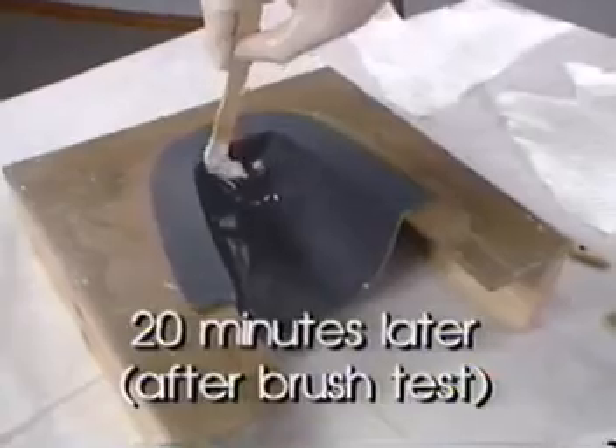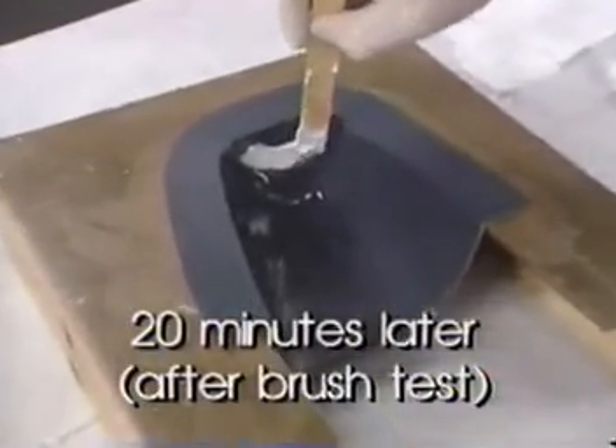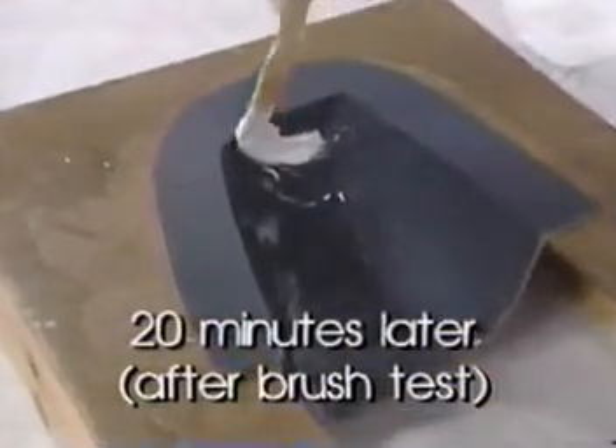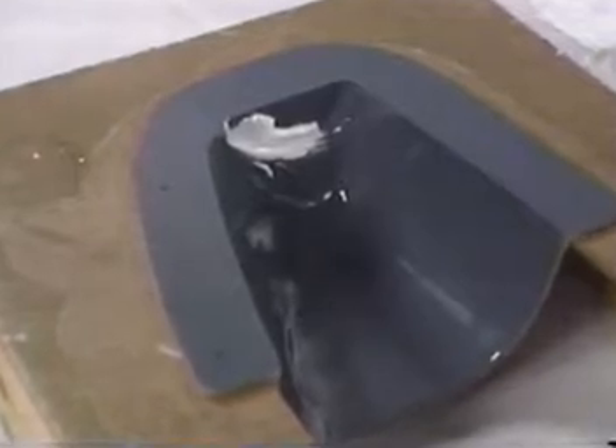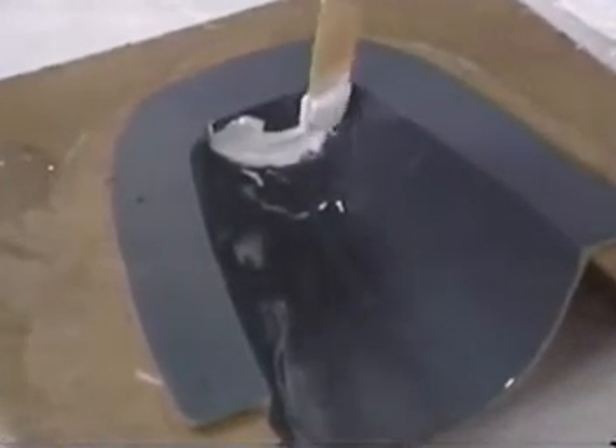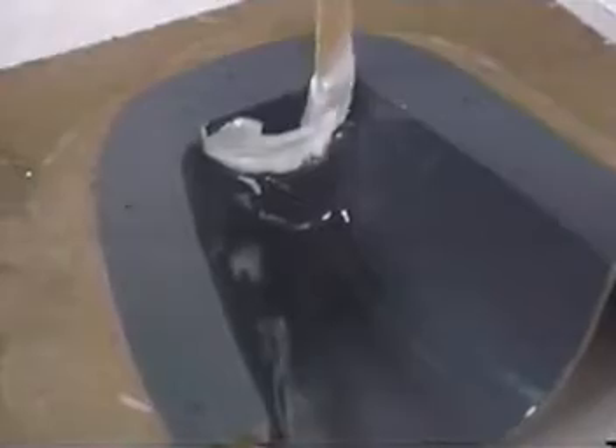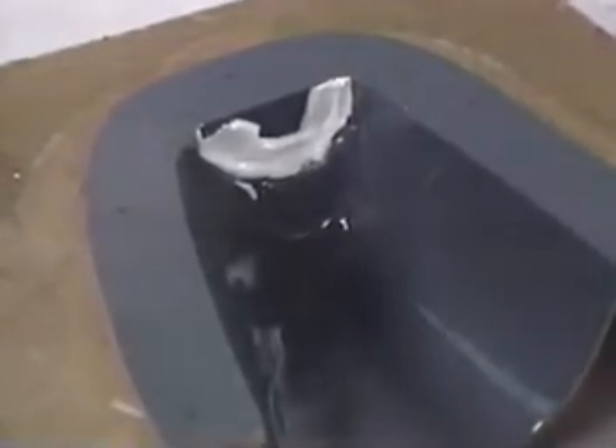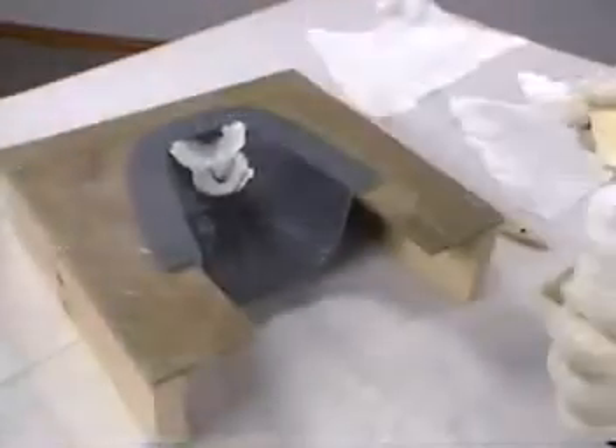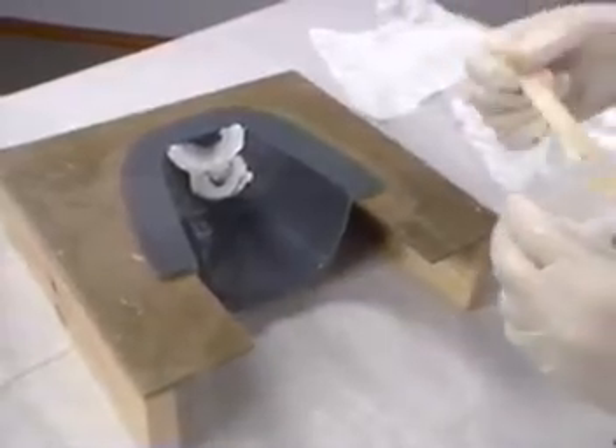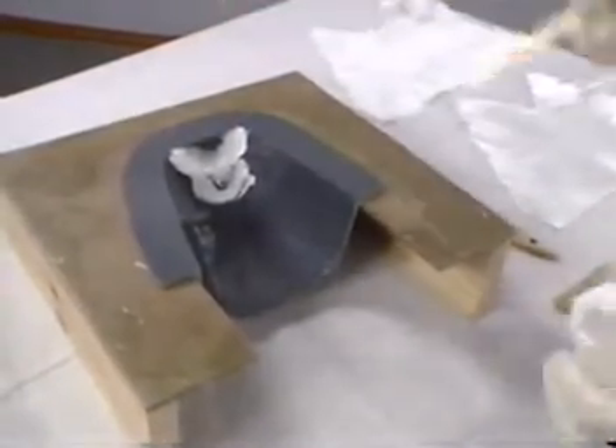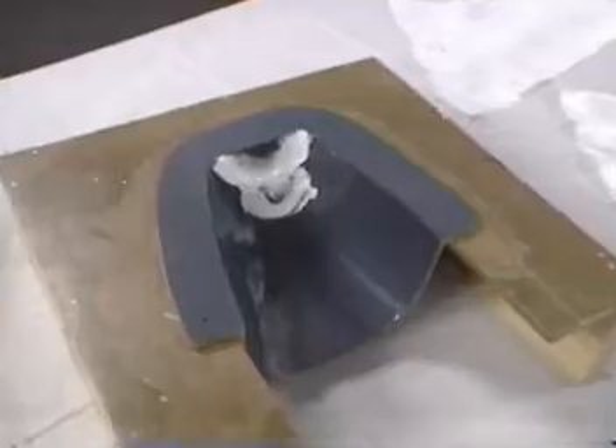Because the cowling has some small edges, Dennis mixes a small batch of the number 22 paste. He sparingly fills in small voids. Excess resin is not desirable because resin alone without fiberglass is not particularly strong and can be quite brittle. But filling these small areas in is preferable to possibly leaving a void causing a weak spot.